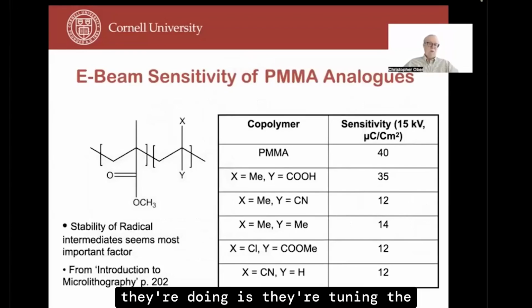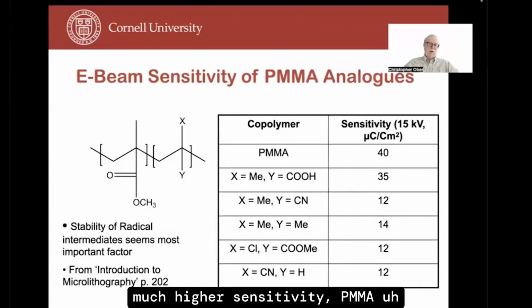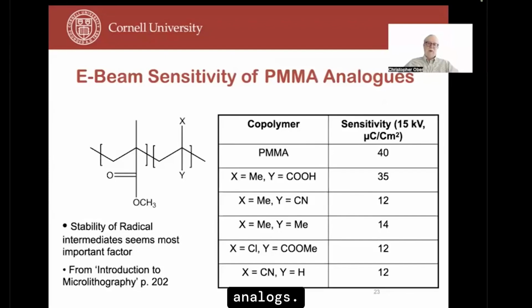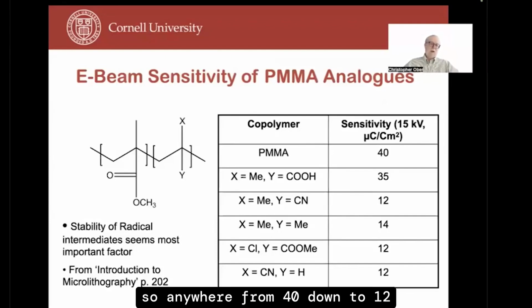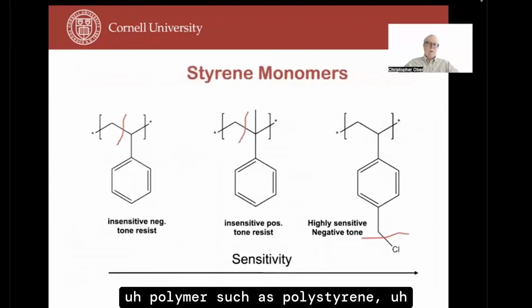What they're doing is they're tuning the stability of the radical and giving the unzipping reaction more time to occur. So this table shows some of the compositions you might find for much higher sensitivity PMMA analogs, anywhere from 40 down to 12 microcoulombs per centimeter squared.